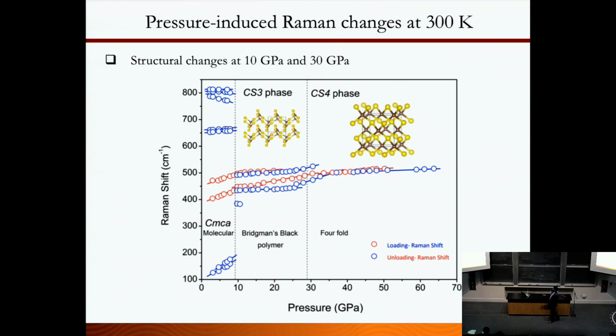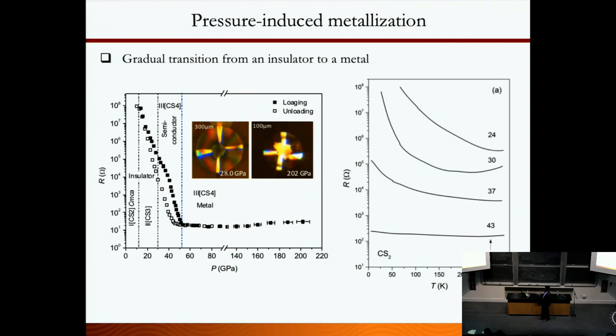And if you squeeze further, you will see this. This is the pressure versus Raman frequency. As you go up in pressure, you can see all the stretching modes and lattice modes disappear, and two new lattice modes appear. Then if you squeeze further, those two modes merge into one peak, whose Raman frequency corresponds to the carbon-sulfur single bond frequency. So it indicates that, as theory was predicting, we are getting into a single bonded network structure of carbon and sulfur.